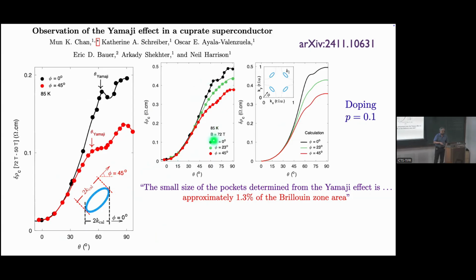And here are their calculations of the magnetoresistance as a function of angle, again from a Boltzmann equation. This is the data, plotted in a way that shows very clearly there is a very special angle, the Yamaji angle. From the Yamaji angle, which you can measure at different values of phi, the direction in the plane, you can read off the size of the Fermi surface. They came up with a number, approximately 1.3% of the Brillouin zone.